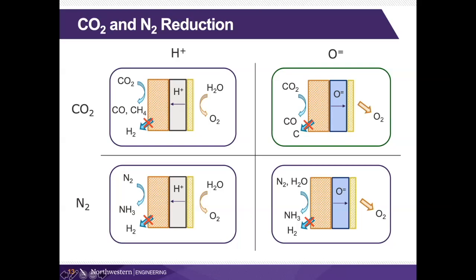So if you're interested in CO2 reduction, it actually makes a lot of sense to use the oxygen ion conductor because here you simply pull off oxygen from the CO2. The reaction that you're competing against is carbon deposition, which is not terribly favored. So this actually goes quite well for CO2 reduction. If you want to make more interesting molecules, that becomes a challenge. But for CO production, this is very straightforward.